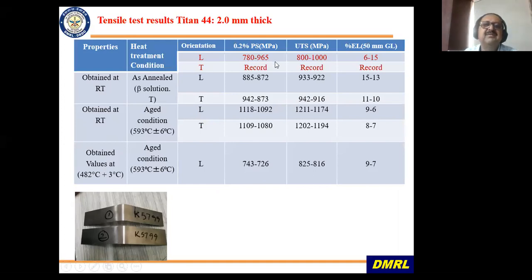Just for the sake of it, I have given you, in case somebody is interested, we can go into the details. 21S is used in beta solution treated condition, and then when you age it, it goes to a higher strength level, and so after you form the component, you can age it so that it gains higher strength. This is most of the sheet alloys. You do a bend test to basically check whether you have any alpha on the surface or not.